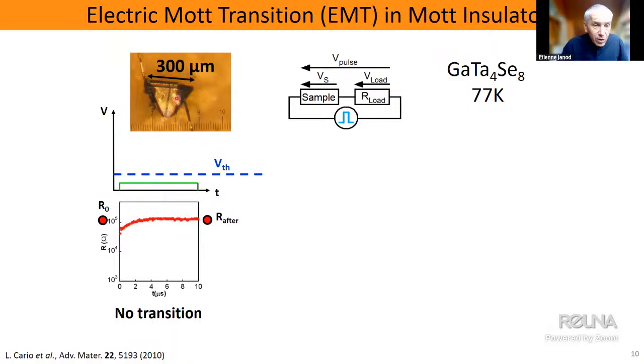We first worked on a single crystal of this GaTa4Se8 compound. We just mounted electrodes, and then we started to apply electric pulses. Here you see in this example, when we apply a pulse which is not very intense, at low voltage, the resistance that we read during the pulse, a pulse of 10 microseconds, is the same as the low bias resistance measured before and after the pulse. Don't pay attention to this initial part, it's just a capacitive effect.